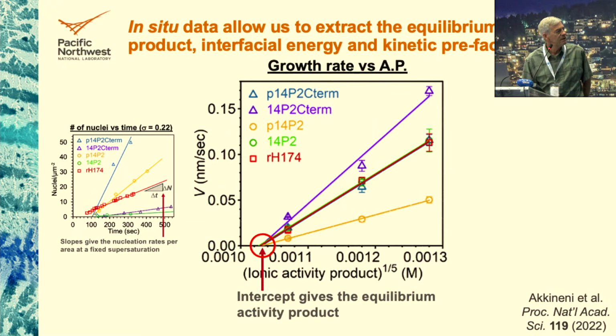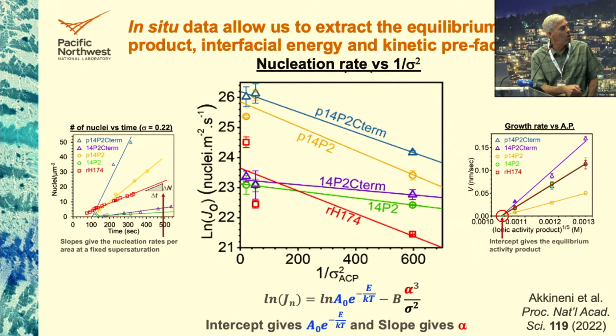We did this as a function of a number of supersaturations. Now, we also can measure the rate of growth of the particles, and we can do that as a function of the ion activity product in the experiment. And those will extrapolate back to 0, which is the activity product at equilibrium, right? So if we want to know the supersaturation, we need to know both the actual activity product, which we set, but we also need to know the equilibrium activity product. And so we get it experimentally by finding out where equilibrium is. This is a very standard way of figuring that out. So now with that information, we have supersaturation, and now we can plot the log of the rate, which we get from these slopes, versus 1 over sigma squared, which we get from the known activity product and the equilibrium point. And from these slopes, we can pull out the interfacial free energy, and from the intercepts, we can pull out this kinetic prefactor.